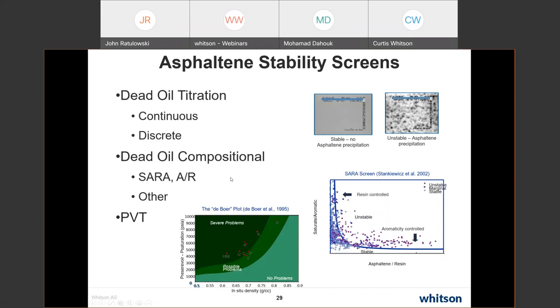There's dead oil compositional screens. So these are usually based on SARA data. There are some that use just asphaltene resin ratio, and there are probably others, but these are the ones I'm familiar with. So here you can see a SARA screen that was developed at Shell while I was there. And if you have saturated over aromatic ratio and asphaltene over resin ratio, you can see where it plots, and that can give you an idea of whether your fluid is stable or unstable.